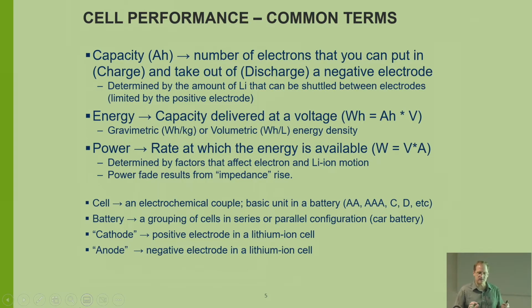Now, capacity is the number of electrons that you can put in a negative electrode during charge or take out of a negative electrode during discharge. And you usually measure that in milliamp hours per gram. So kind of a way of electrons per gram in that material. Then energy is the capacity times the average voltage. And power is voltage times current. So it's the rate at which you can deliver that energy. I know a lot of times you read newspaper articles, they mix up the terminology for power and energy. But power is, like you think of horsepower, or watts, kilowatts. Energy is like joules, or how much actual heat you get, how much work you can do.